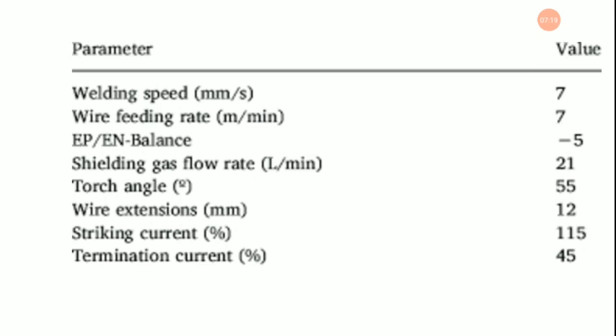Now, the effect of welding speed on depth of penetration. Readings of the depth of penetration obtained through measuring instrument after cutting all the welded specimens perpendicular to the direction of welding are analyzed with the help of a graph and is plotted between welding speed and penetration. Voltage 24 volt and current 105 ampere are taken constant, and arc time is varied during the welding of specimens. The depth of penetration increases with increasing welding speed up to 110.39 mm per minute, which was the optimum value to obtain maximum penetration, because it begins to decrease linearly after this point.